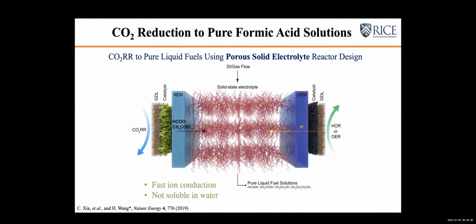This can also help us separate the liquid, while the fast ion conduction can still be well maintained by this solid electrolyte between cathode and anode. At the same time, the solid electrolyte won't dissolve into the water. So once you have a deionized water stream flowing through the pores of the solid electrolyte layer, the generated liquid fuels can be continuously collected by the DI water. In that case, you don't have any potassium ions, sodium ions, or bicarbonate ions in your downstream formic acid solutions.